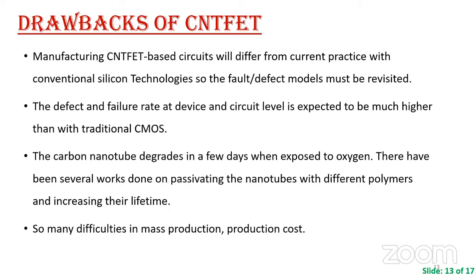There are some major drawbacks for CNT FET. The main drawback is that the defect and failure rate at device and circuit level is expected to be much higher than traditional CMOS. And manufacturing CNT based circuits will differ from current practices of conventional silicon technology, so the fault and defect models must be revisited. And the carbon nanotube will degrade in a few days when exposed to oxygen. There has been several work done on passivating the nanotube with different polymers and increasing their lifetime. There are also many difficulties in mass production cost.